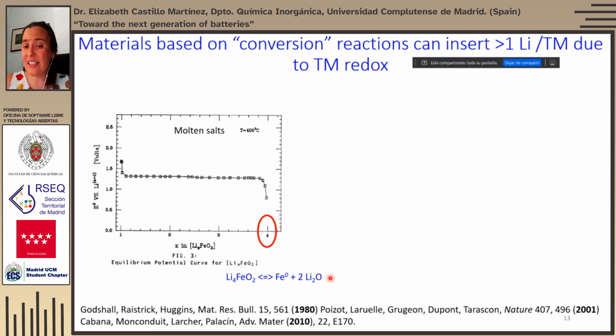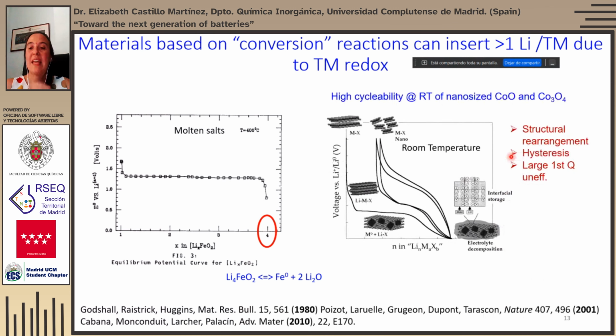So although this type of reaction was known from the 80s, and it was reported for many oxides, nitrides, and sulfides, it was not until 2001, sorry, my slide is wrong, until 2001 that high cyclability was reported at room temperature for nanosized cobalt oxide, in both the rock salt and the spinel crystalline structure. And what is found in the room temperature cyclability is that actually the first discharge plateau is quite different from the following cycles.